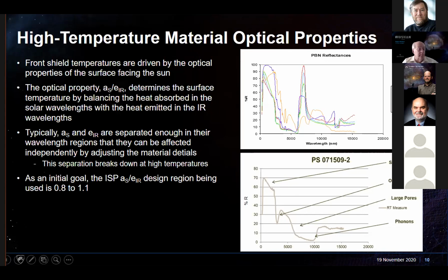We were looking at different kinds of pillars and stuff like that, but the point is that for a given kind of material, you get a given reflectance. The reflectances in the short wavelengths are due to the pore size and the porosity, how you sprayed your plasma sprayed coatings, the particles you used, and how those turn into splats on the surface. So pore size is important. One of the big things you do in ceramics is try to get rid of pores. In a reflective system, you try to encourage pores in these short wavelengths because that's where the reflection is happening. But then you have to worry about how these things change, right?